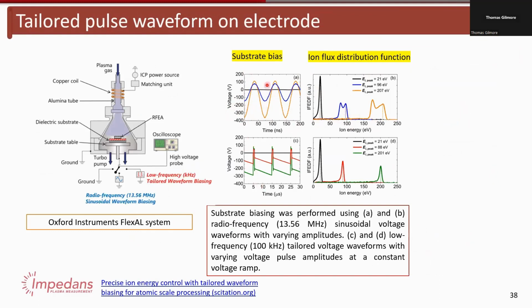But you don't have to apply a sine wave, okay? So what happens if you apply power with a specific shape? In this case, it looks kind of like pulsed DC. You have this narrow spike, and then you have a ramp down. By applying this shape, you actually get these very narrow ion energy distributions.